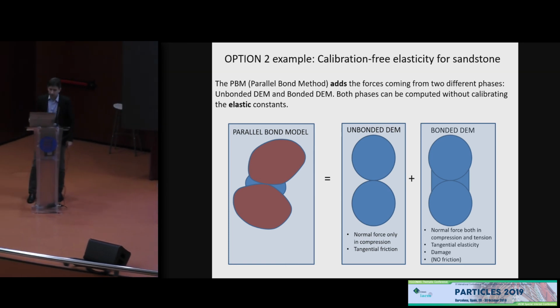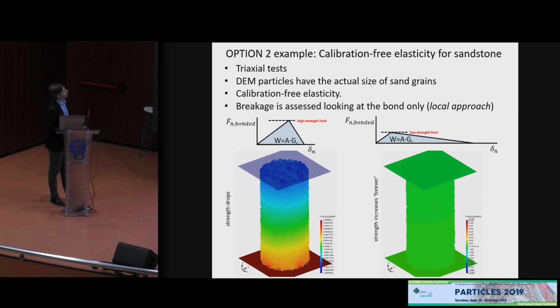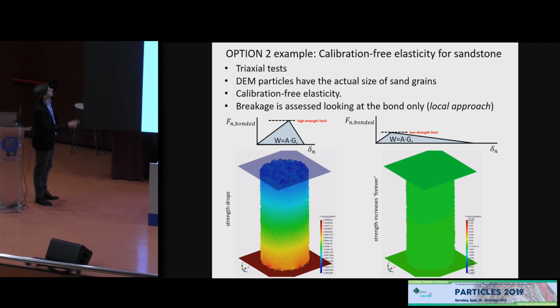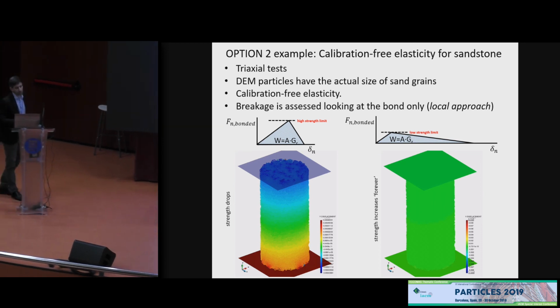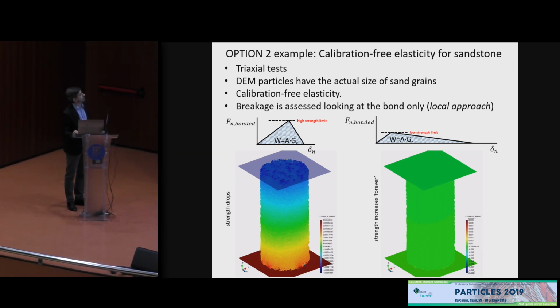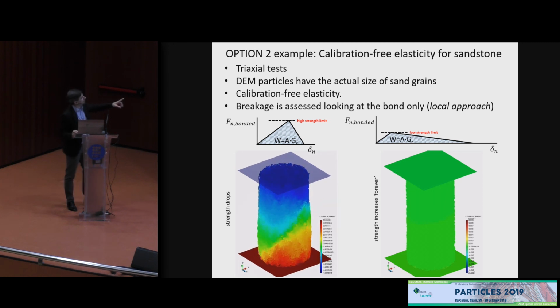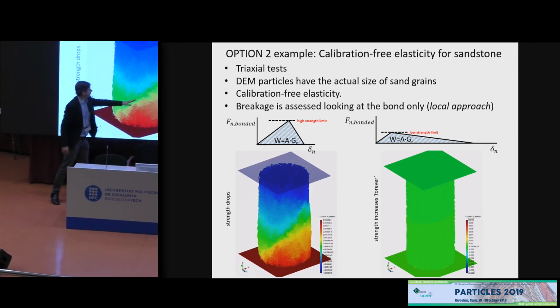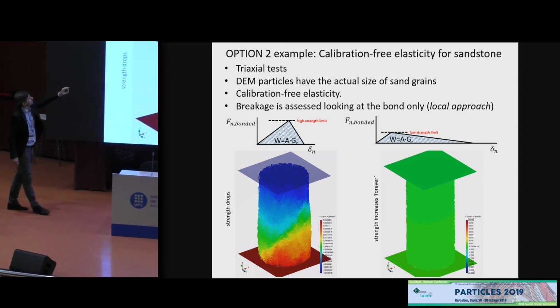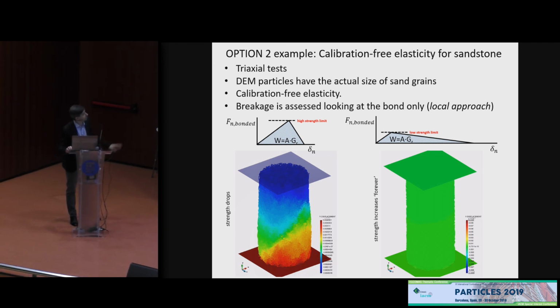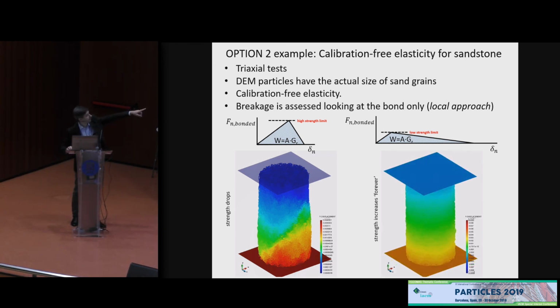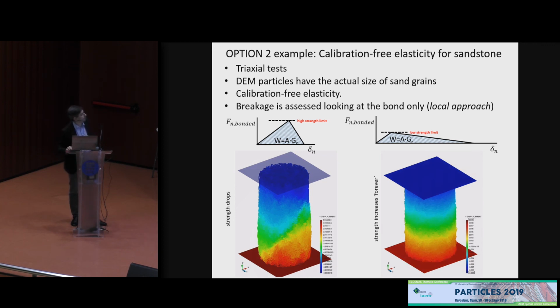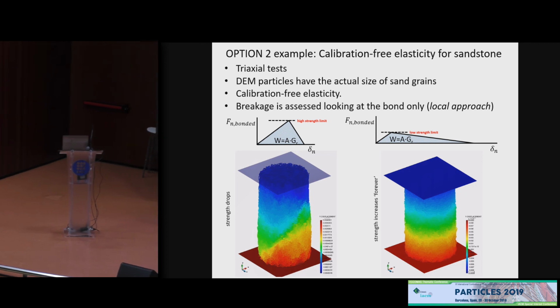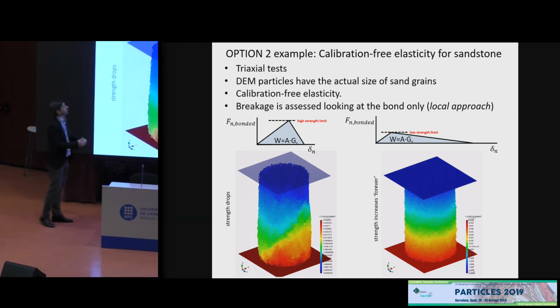And if you do that, you can add also the concept of fracture energy. And we did some triaxial tests. This is not the scope of the talk, because the scope was to transfer the ideas to you of what I said. But we have here a shear band where we are using high strength limit and a certain fracture energy. But if you keep the same fracture energy and decrease the strength limit, then you don't have this shear band, because the material gets very ductile, very like chewing gum, say.